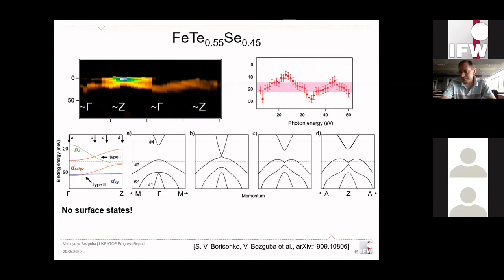Yeah. All these experiments which came out in these papers, they're fine, but they are not fine in the sense that this material is still not suitable. If you find a material where this inverted tiny gap is at the Fermi level, then all these stories come back and one has to measure the right material. But these stories are STM. Mostly, yeah, as far as I know, they're mostly STM.